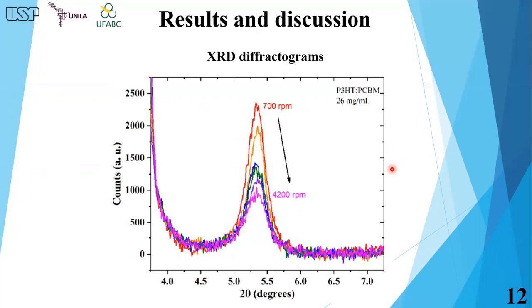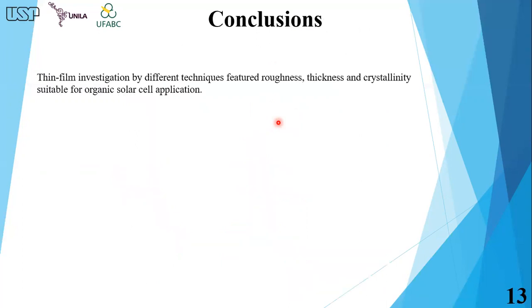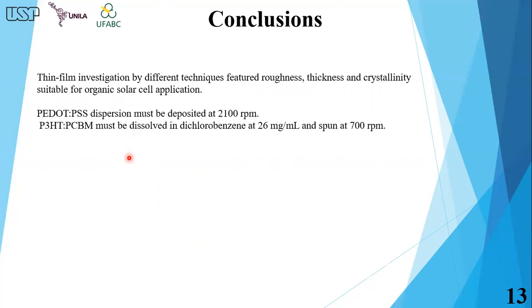26 milligrams per milliliter and 700 RPM seem suitable for organic solar cell application. Thin film investigation by different techniques showed roughness, thickness, and crystallinity suitable for organic solar cell application. PEDOT:PSS dispersion must be deposited at 2100 RPM. P3HT:PCBM must be dissolved in dichlorobenzene at 26 milligrams per milliliter and spun at 700 RPM.